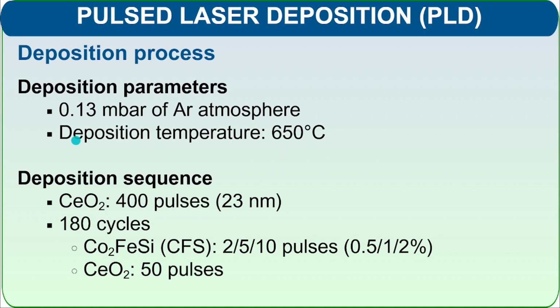The deposition sequence was as follows. We grew a 23 nanometer layer of CeO2 initially. Subsequently, we performed 180 deposition cycles in which we alternated between the targets. For each cycle, we applied 2, 5 or 10 pulses to the CFS target, followed by 50 pulses on the CeO2 target. In the end, we have films with 0.5, 1 and 2% of the dopant content respectively.